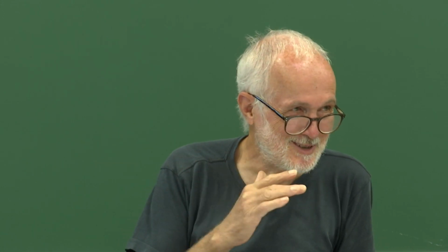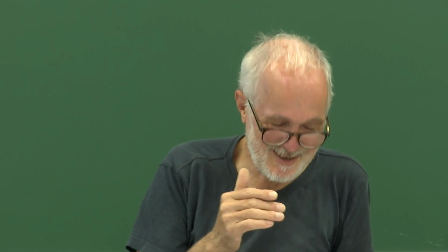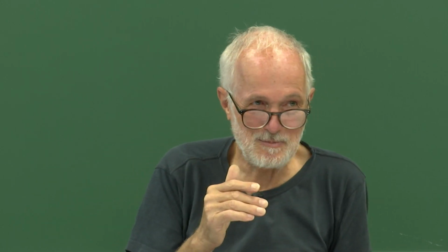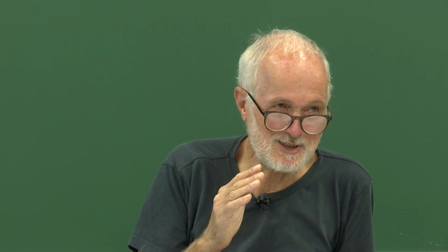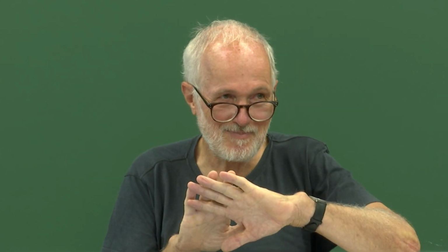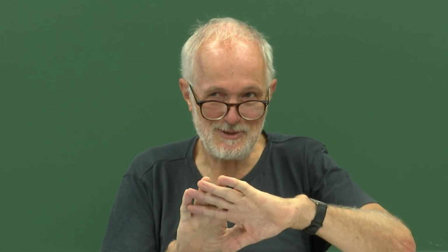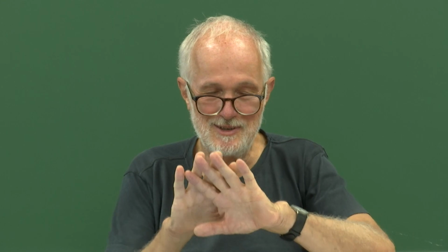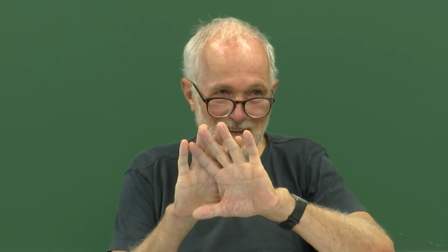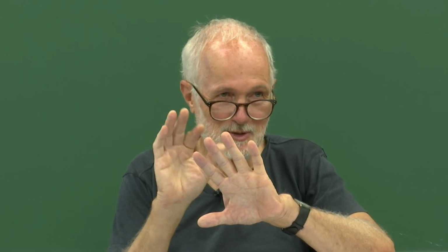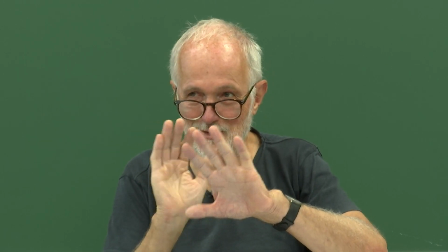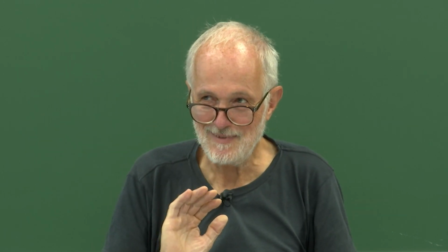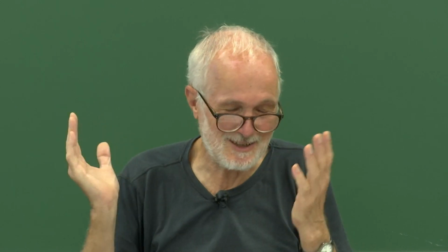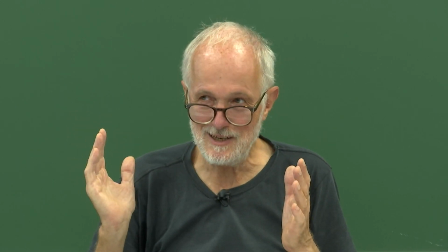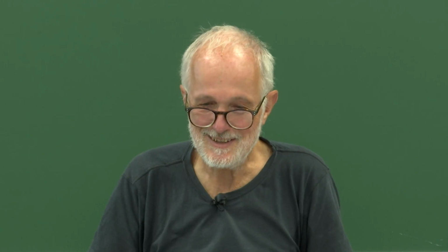And similarly, you find it also if you do a two-dimensional simulation. I think we showed these examples - perhaps I'll show them in the next lecture on Introduction to Monte Carlo. In a two-dimensional system, if you use a square lattice in a 50% ordering, you find a second order phase transformation. If you use a triangular lattice with a 1/3 occupation, so you have 3 sublattices, you find a first order phase transformation. And you nicely see this metastability there. I'll show it in the next lecture.